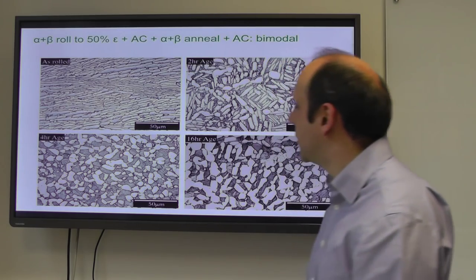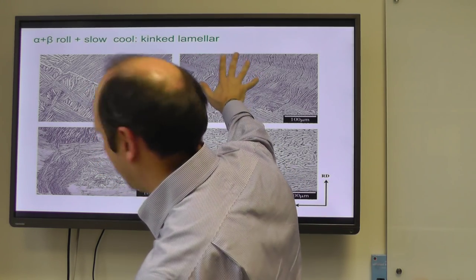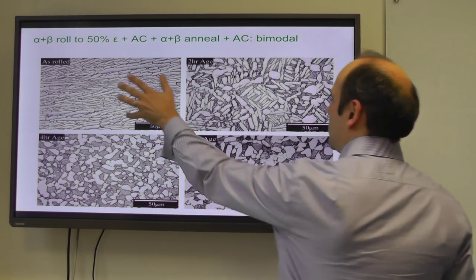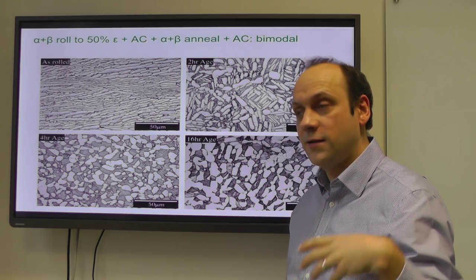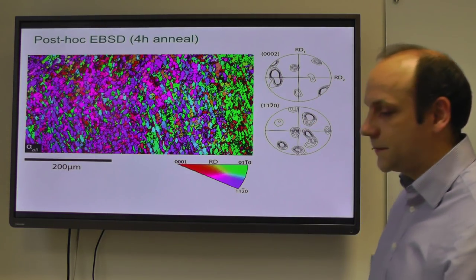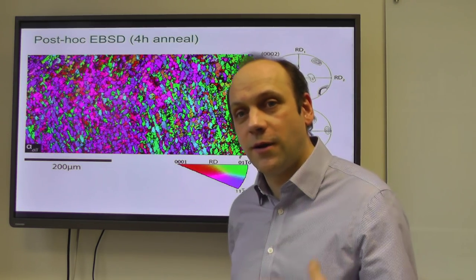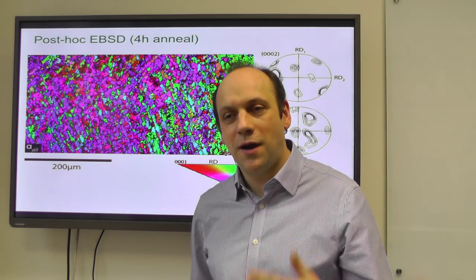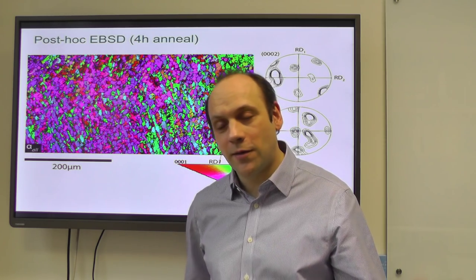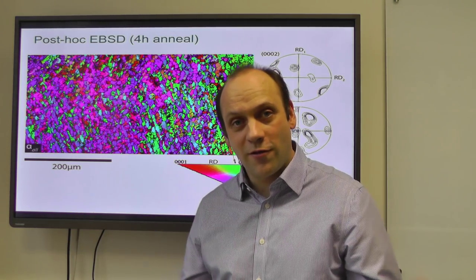One key issue is that all the plates within a colony were at the same orientation - they all deformed in similar ways. When they recrystallize they all come from the same parent grain, so they're all at the same orientation. So all of the primary alpha from a given colony will actually be similar orientations. While you've achieved a fine-grained microstructure of 20-micron primary alpha, if all those grains are the same orientation you haven't necessarily improved matters very much. The lamellar alpha in between is supposed to stop dislocations running from one primary alpha to the next, as if they were all one grain.